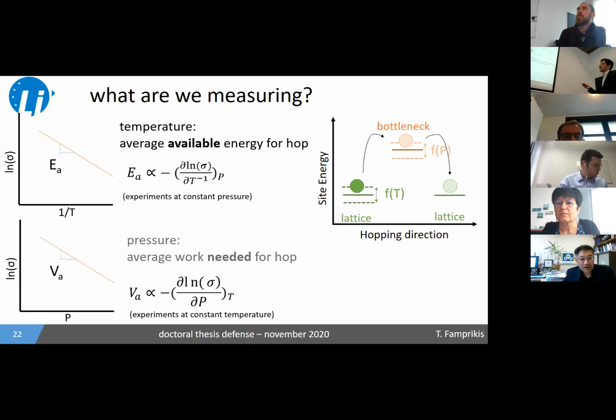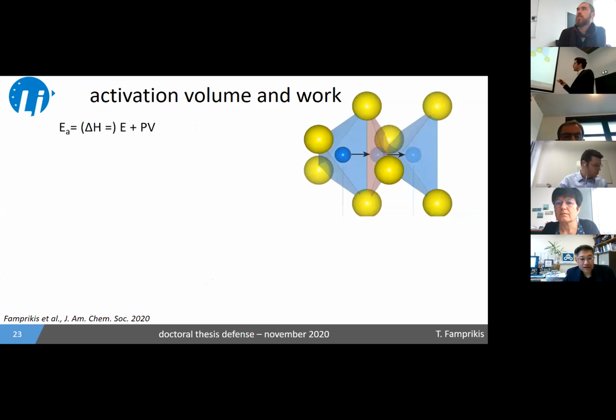And what the activation volume basically tells you is, by varying the pressure, what you actually do is you change the average work, the mechanical work that is needed to be done in order for the ion to enter the bottleneck. So you're basically playing with the energy level of the bottleneck up here. So I'm talking about volumes and work, but what does it actually physically mean? You see here a representation of the actual situation in Na3PS4. And the key somehow to understanding what I mean by work is to